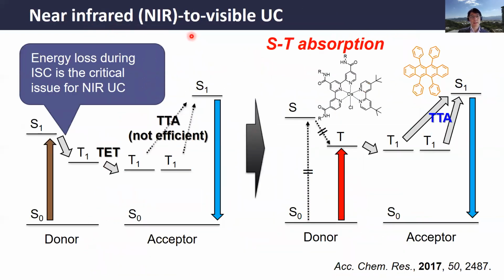So my last topic today is near-infrared to visible upconversion. It was difficult to upconvert near-infrared to visible because of the energy loss during the intersystem crossing from S1 to T1 of the donor. So we propose to use the S-T absorption, that is the direct transition from the ground state to the triplet state. So you can skip the intersystem crossing and avoid the energy loss. So we synthesized this osmium complex. This shows a nice near-infrared S-T absorption thanks to the heavy metal effect of the osmium ion.